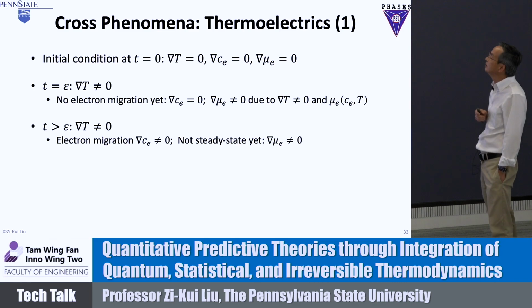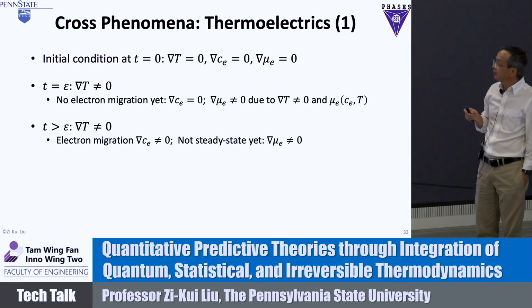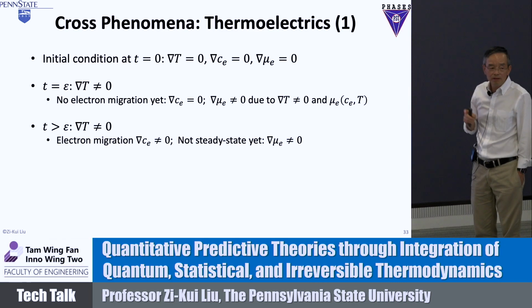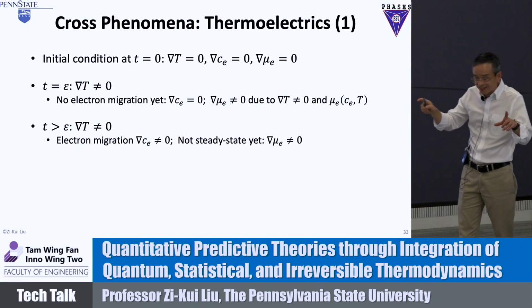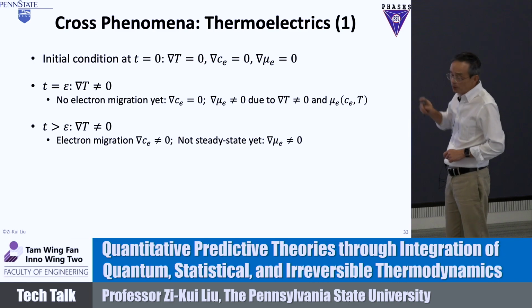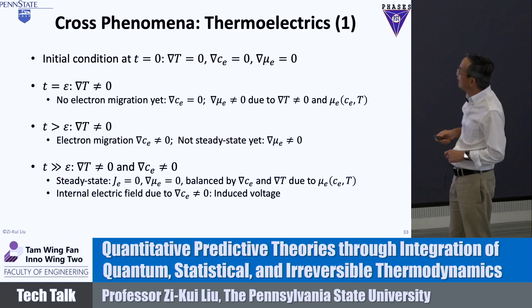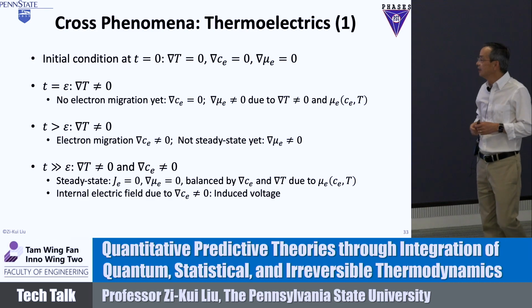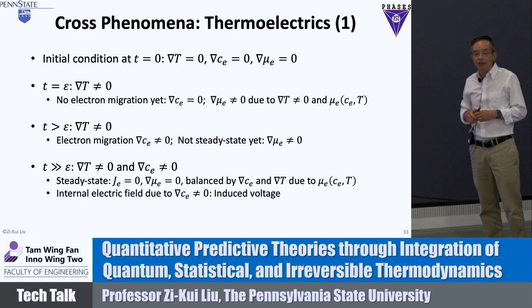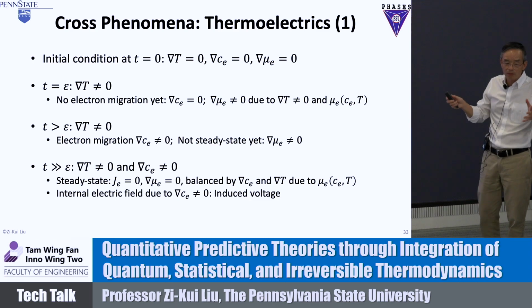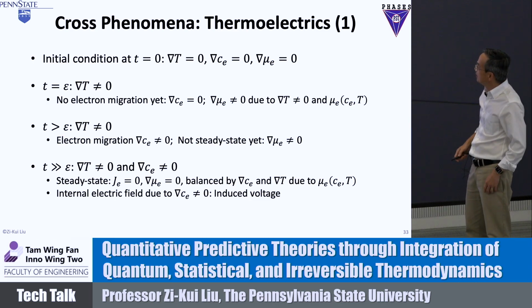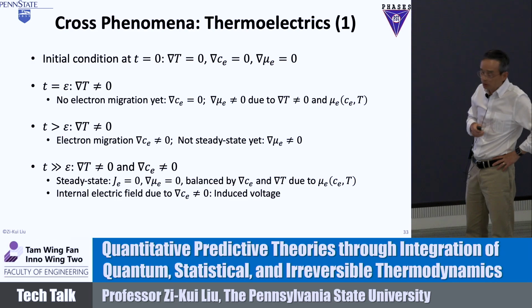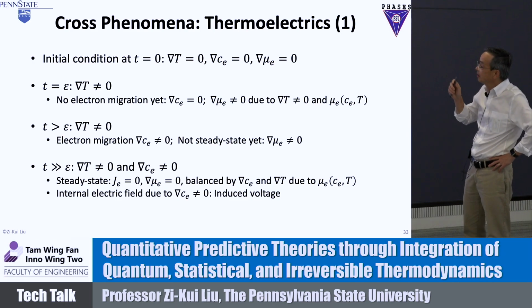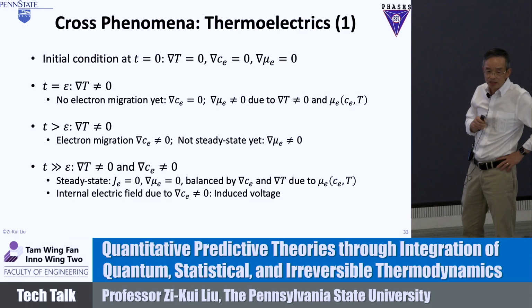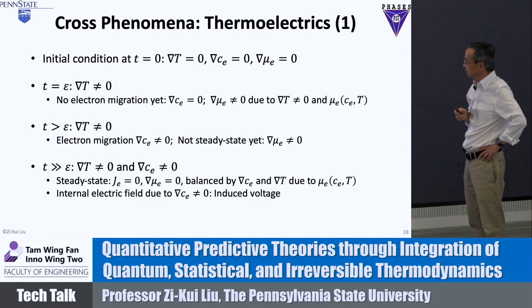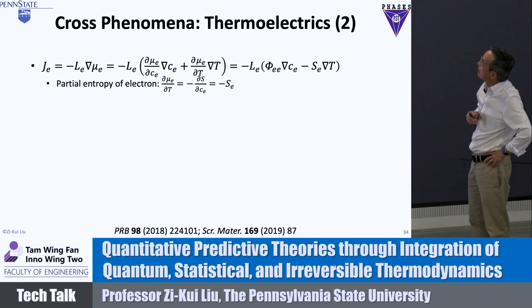So the electron moves. Because there is no current flow, after a while there will be a concentration gradient of electrons in the system. At that time, the chemical potential is not 0 yet. It continues to move until at some stage the chemical potential of the electron equals 0. There's no current flow anymore. The electron stops. Electrons move very fast. That's where you measure the Seebeck coefficient. What does it mean? The Seebeck coefficient is a purely thermodynamic function, the derivative of the chemical potential of the electron with respect to temperature. So we can calculate one.